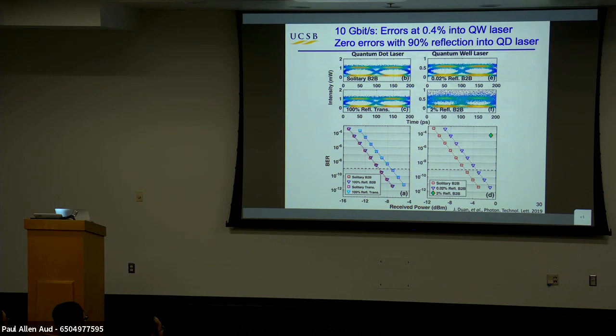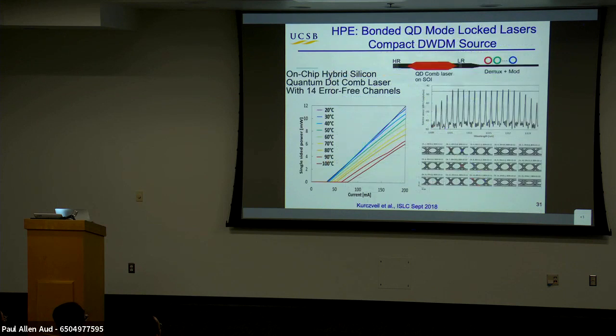And so in our earlier results, we did not have the narrow distribution of dots, and indeed you do see a larger alpha, and you see more reflection sensitivity. So here's an example now. I'll show two systems experiments of what one can do.